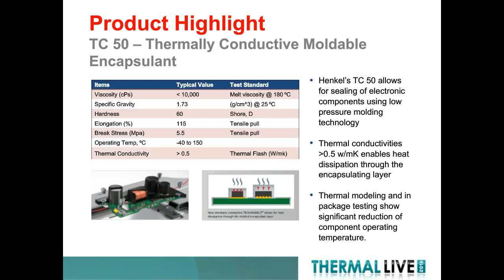From a product standpoint, a technology standpoint, again, I talked about viscosity, hardness, elongation, and break strength previously. What we see is an operating temperature of minus 40 to about 150 degrees C. This material is going into RTI certification now. With that thermal conductivity, we expect good things for both those ratings to come out. In the two images below, you see a LED driver board being molded, or a mock-up of it being molded, and then placed into its frame.